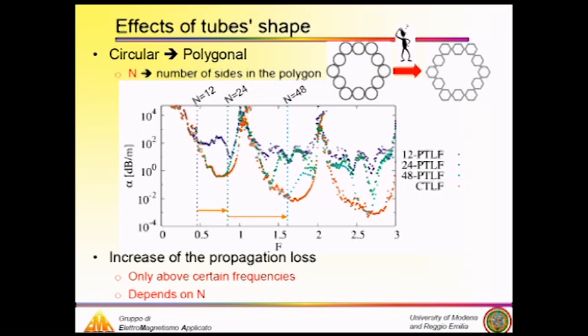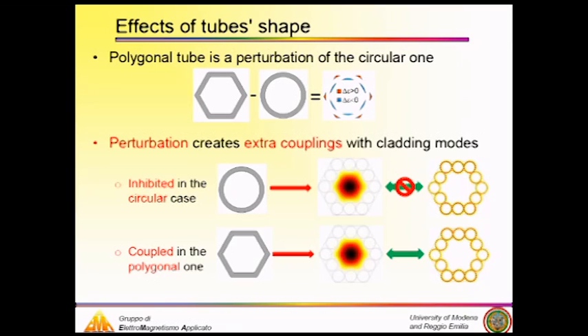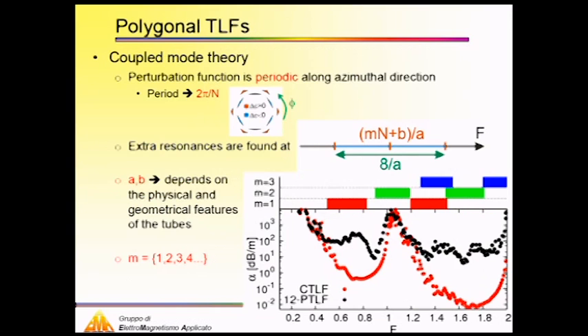So this can be taken into account considering the fact that the polygonal shape can be seen as a perturbation of the circular one with this kind of perturbation function. If we take this into our coupling model shown before, we can state that this kind of perturbation allows, in the polygonal case, resonances that in the circular case were inhibited. So, carrying out calculations and considering the fact that this perturbation is a periodic function along the azimuthal direction, it is possible to determine the spectral position and spectral width of this increased loss region given by this formula here, in which A and B are parameters that depend on the geometrical characteristics of the circular tube taken as a reference, and M is a generic integer value.